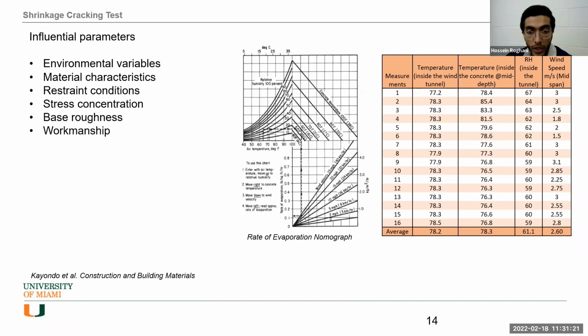And what is the role of that stress riser? It forces the crack to occur in the desired location by a sudden change in the cross section, making a weak area at the mid-span. So in that area, you will have a smaller amount of concrete that can crack earlier. If we don't provide the riser, we may see small map cracks in different sections that make the investigation more complicated. You have to monitor the entire section and do several measurements, because when you have cracks everywhere, you will have stress release in different parts that cause more cracks, but tight cracks. So it's better to have something at the mid-span, which is wider, so you can study it better, compare the results better, and see the difference better.